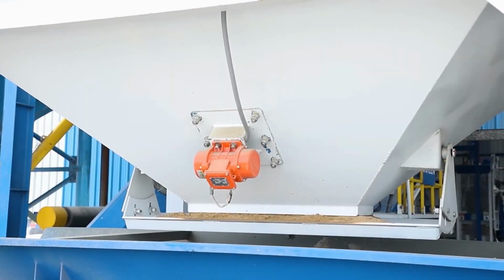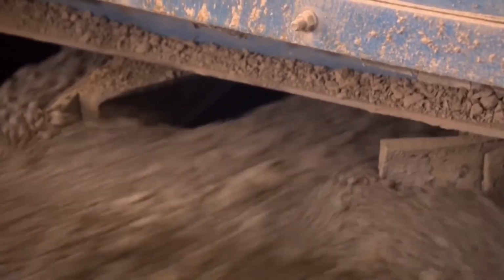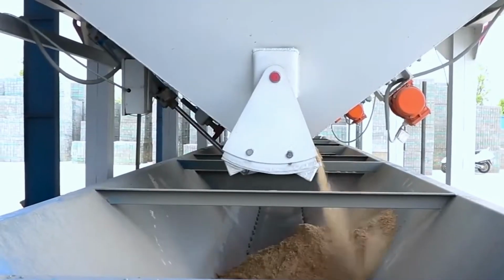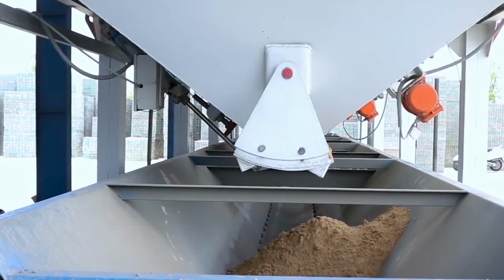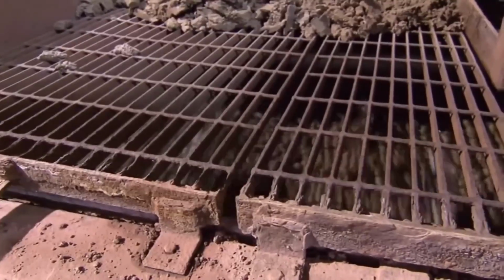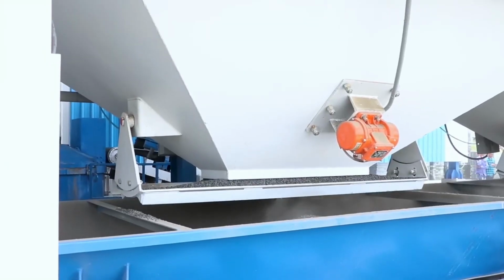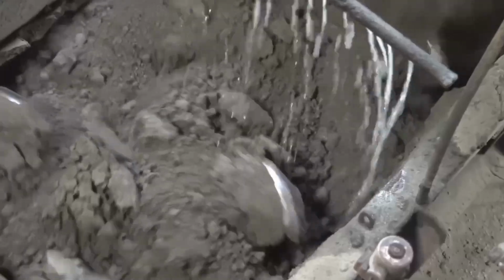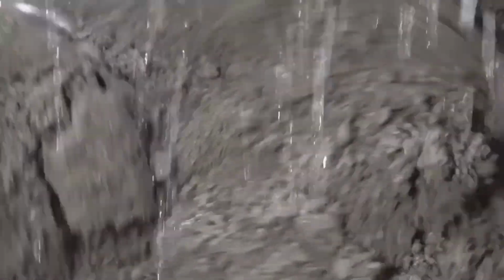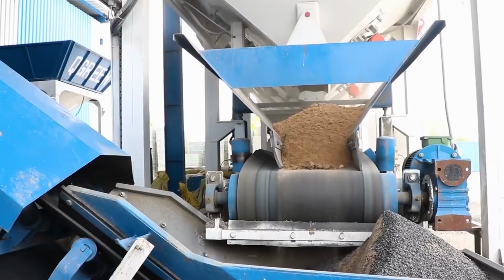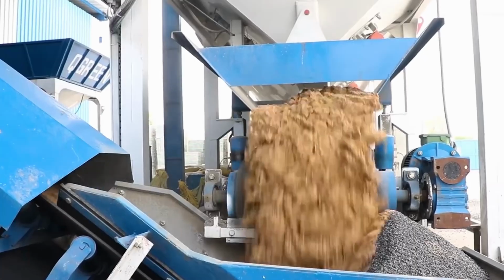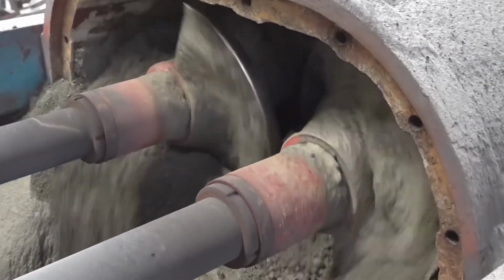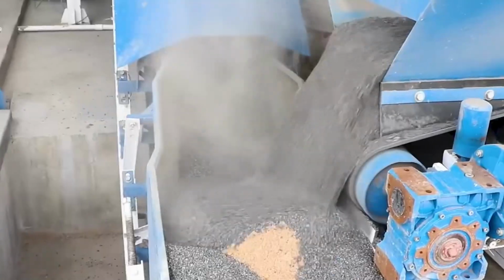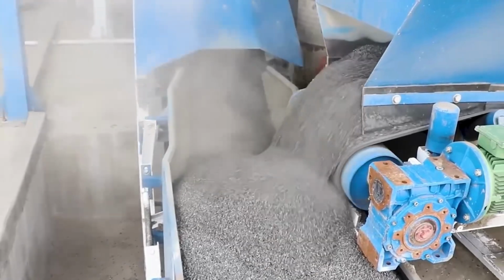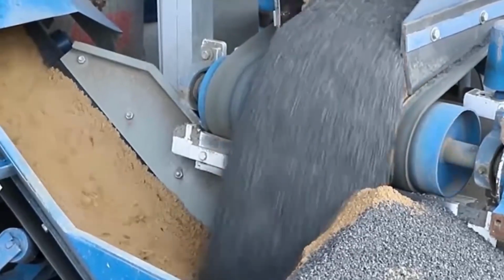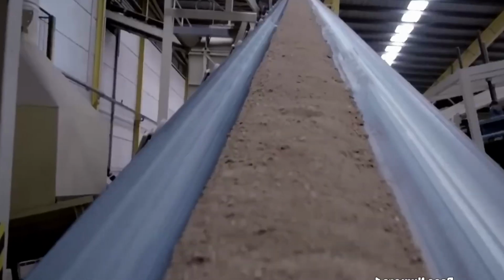After the initial crushing, the clay passes through roller mills. Two heavy cylinders rotate in opposite directions, crushing the material to a controlled size. Any stones or hard nodules are broken up or separated. In the most advanced factories, sensors and screens remove particles that could cause cracks or warping. A small stone trapped inside a brick can expand during firing, crack the piece, or create a visible stain. This is why cleaning and grinding are so important.